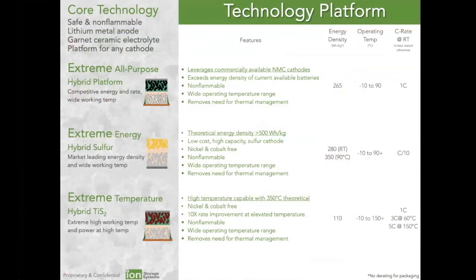And these are some of the specifications of the cells that the company is developing using this platform. The one on top is this bilayer where we're using an NMC cathode. We're achieving 265 watt hours per kilogram, but now completely safe because it's a ceramic electrolyte with all non-flammable components. So it removes that safety concern.